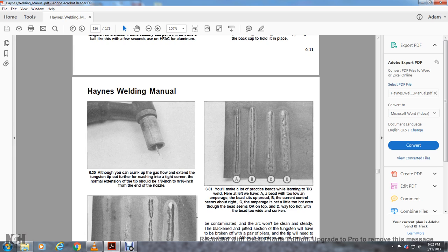You can make a lot of practice beads while learning TIG, and here are some examples. A, the amperage is too low and the bead sits up proud. B, the current control seems about right. C, the amperage is set too high, even though the bead seems okay on top. D, way too hot, with the bead too low, too wide and sunken.